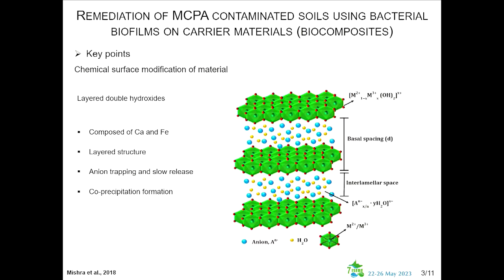I talk about surface modifications of carrier materials, and in this project we chose to cover the carrier materials with layered double hydroxides, which are compounds with a layered structure. The layers are composed of calcium and iron hydroxides, and we can have the presence of water molecules and different anions between layers.